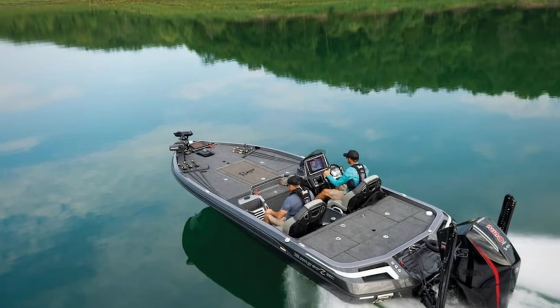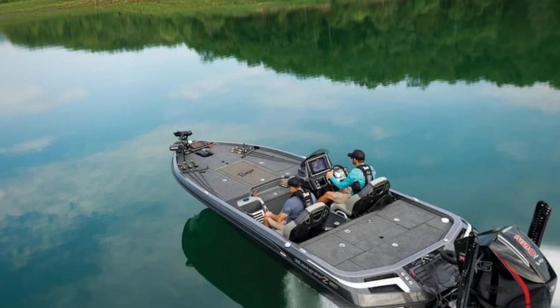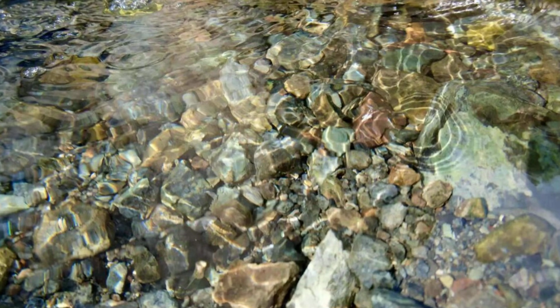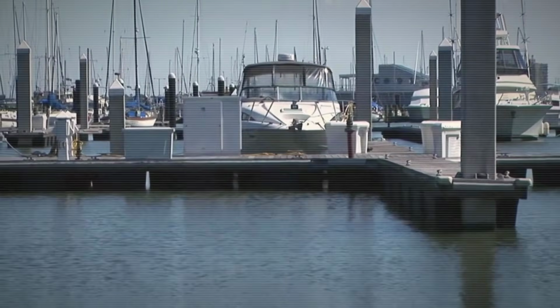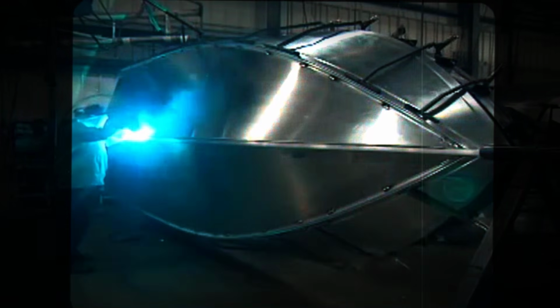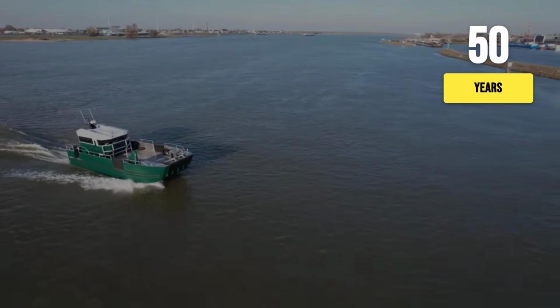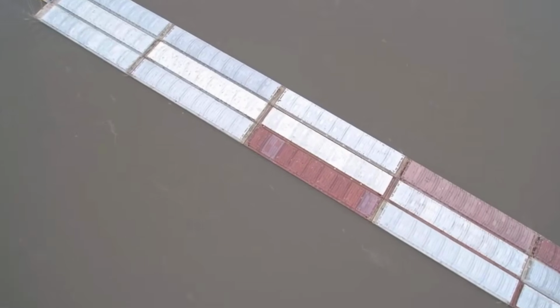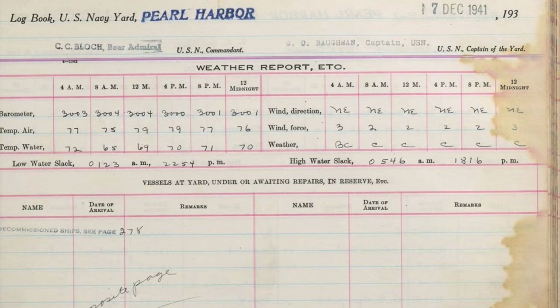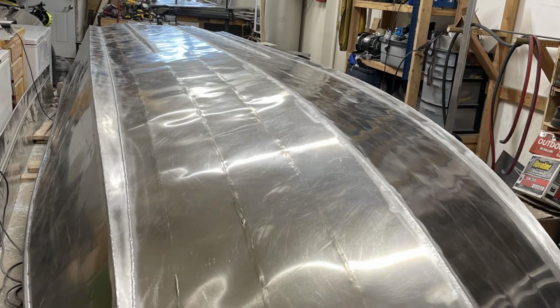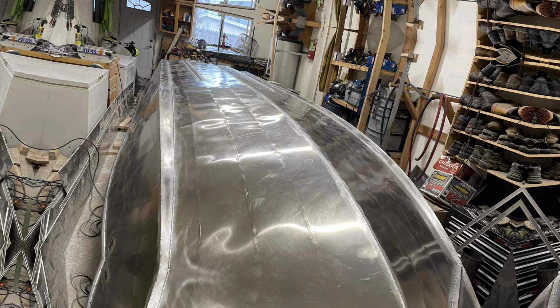The environment determines the verdict more than the material does. In freshwater, aluminum's electrochemical threat is dramatically reduced. Freshwater is a weak electrolyte. Electrical current moves through it slowly, galvanic reactions run at a fraction of the rate they do in saltwater, and stray current corrosion from marina infrastructure is far less common. Properly built, welded aluminum boats in freshwater environments routinely reach 30 to 50 years of service life. Many commercial aluminum workboats operating on inland rivers and lakes document service records that fiberglass production hulls rarely match. In freshwater, aluminum is the more durable choice by a measurable margin.